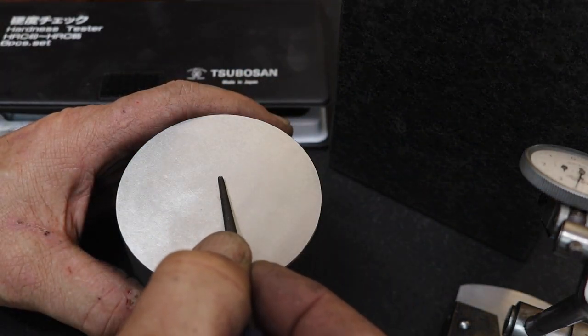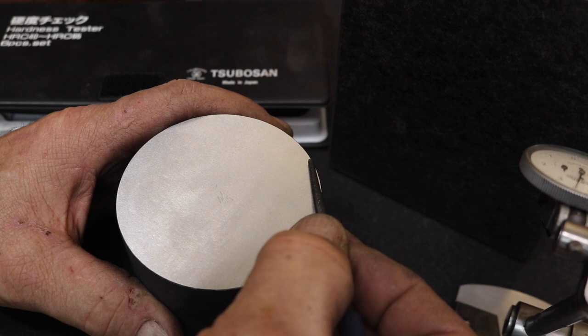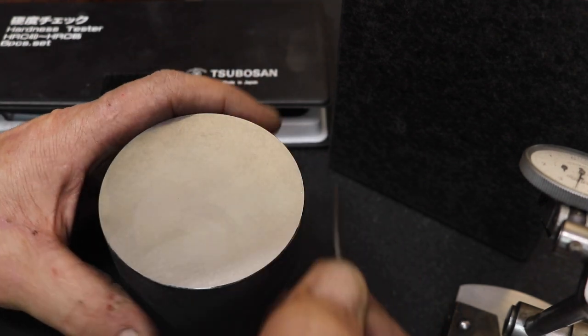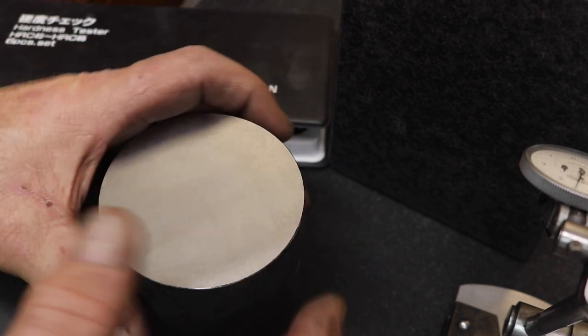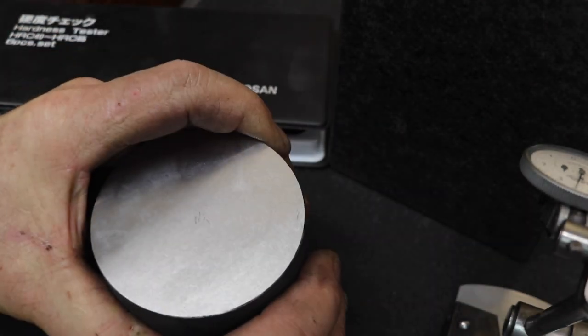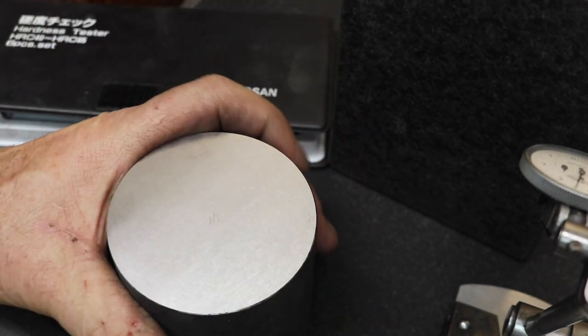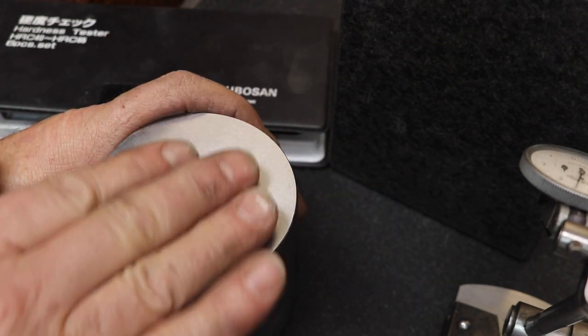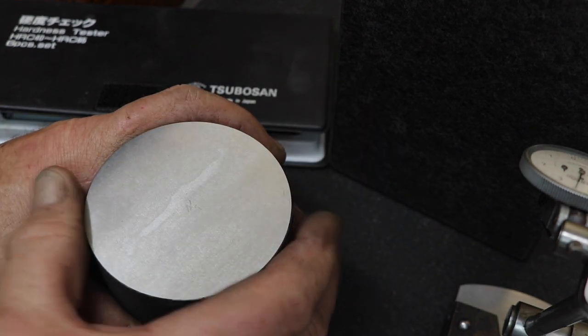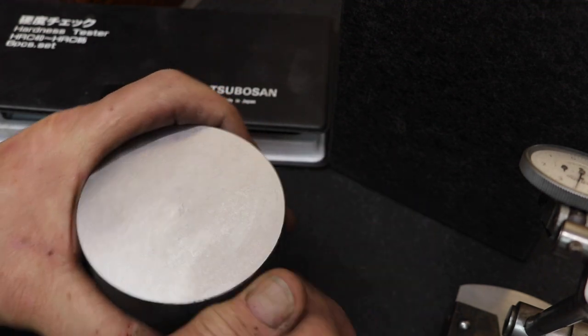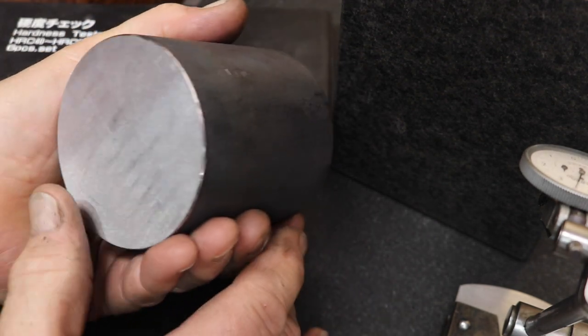This is a 60. Yeah it does grab at 60. Out here at the edges, barely, just barely at 60 out at the edges. So we're probably about 55 in the center and 60 at the edges. Yeah that's nice, came out good. It's an anvil, we're gonna beat on it. Very happy. Usually you don't get up to the 60s with this material, with 4140. But quenching in water like I did, you can get it harder. If you quenched in oil the cooling is slower and you probably won't get to 60. But doing it in water you can actually get it a little harder than the 55. So we're probably right up there closer to 60, which is sweet. And we tempered it, so we're good.